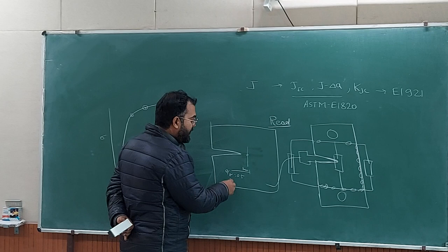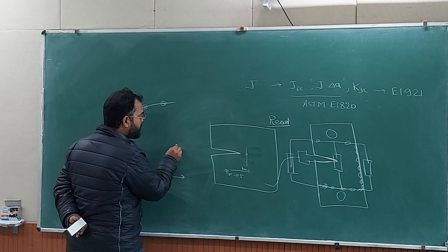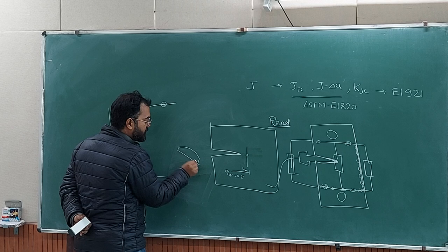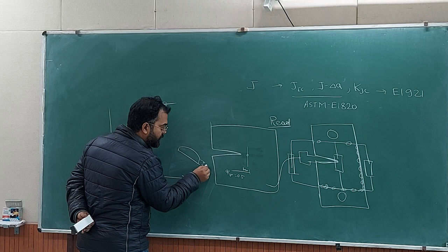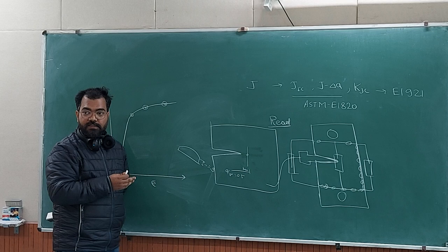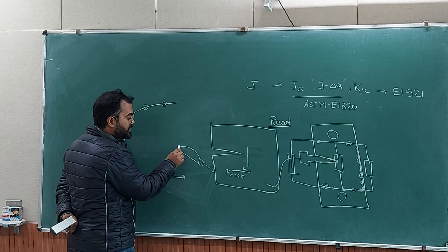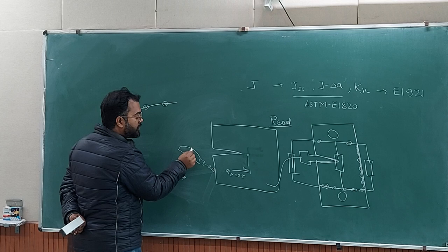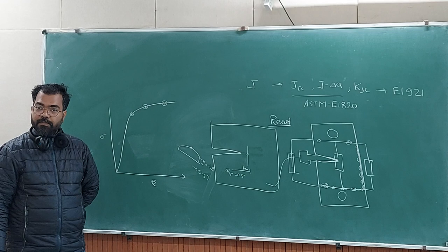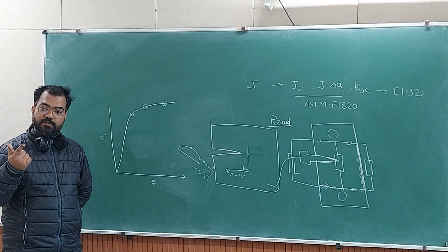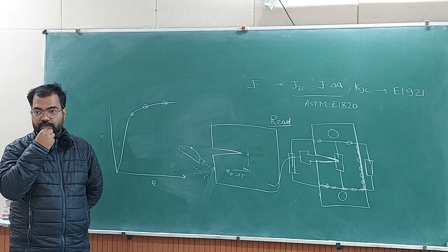So we don't know, this A by W, this crack length will not stop at 1 millimeter. When you have broken the sample, then you will see that the crack tip initially was like this. Here you said that it should be 0.9 millimeter. So in some cases, you don't know what is inside. You can't see what is inside. Okay. So you might have some inhomogeneity or something. If nothing is there, it should look like this. So this might go to a higher value so that the average is a little bit more than 0.5. That can happen. And this difference will be there in each specimen, so you have a different A by W. Well, you are actually ensuring different A by W in this multi-specimen approach, because you want to have different crack lengths. Okay.